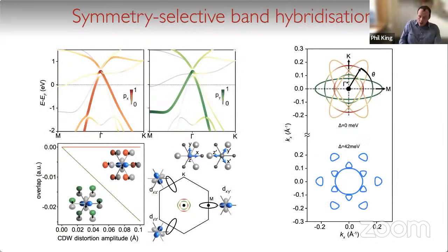So what you've really got at the charge density wave transition here is you've got D states, which are forming the conduction bands in the system. These are then backfolded by the 2x2 lattice distortion, and these couple with the P states from the valence bands. And it turns out that if you look in the octahedral coordinate system, you've got XY, XZ, and YZ D-derived conduction band states for the three conduction band pockets that are backfolded to the zone center. And then you can ask what the hybridization matrix elements are between those particular D states and the PX and PY derived valence bands.